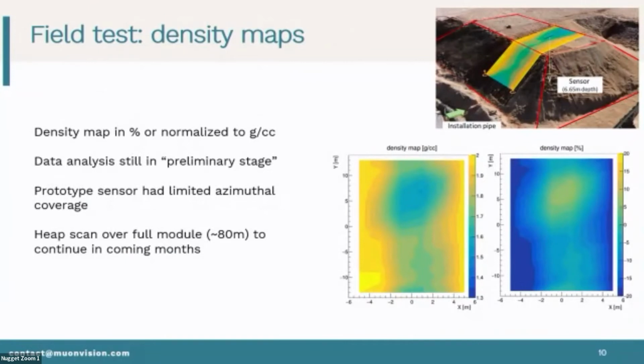Then the other thing is that we can generate the density. Now, to be perfectly honest, this needs to be normalized to what the incoming cosmic ray flux is. We can take a textbook analysis, we can do an in situ measurement, we can do a good job or a less good job. And we also need to know the efficiency of detection. So our normalization factor at this moment is still a little bit uncertain, so I would like to call this an uncertainty. But we can always generate the map which gives you the density variation in percentage, because for that we do not need to know any efficiency. If there is a cosmic ray flux variation, it's the same across the whole map.